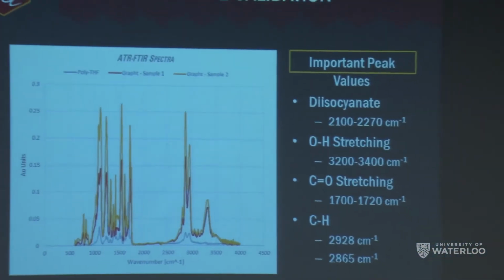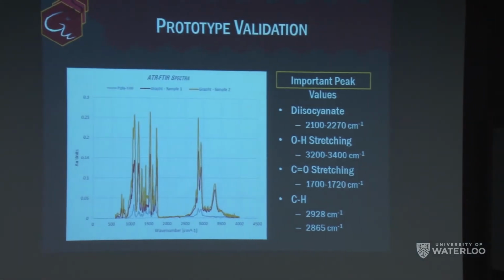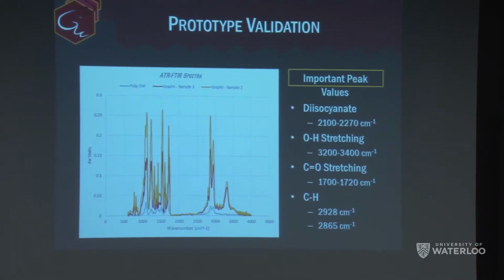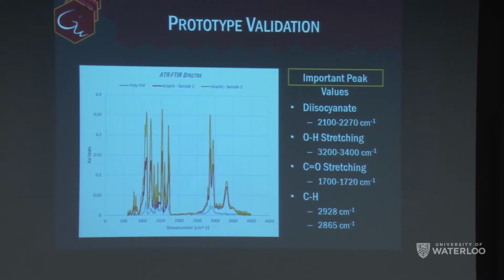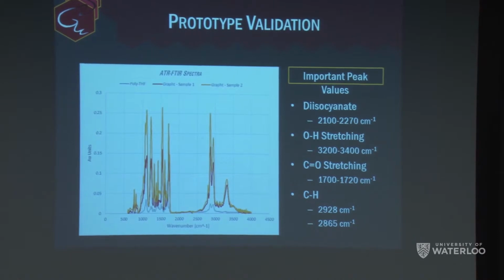We also did ATR-FTIR to make sure that the bonds and the grafting were adequately completed. So the linkage and grafting reaction went well. The first peak that we'd like to look at is the diisocyanate peak, which as you note is not there, which is good. Diisocyanate on its own is somewhat of a health risk. But as you can see from our 2 Grapht samples, there's none left. That means that the diisocyanate was completely consumed during the reaction and attached to the functional groups on the reduced graphene oxide.